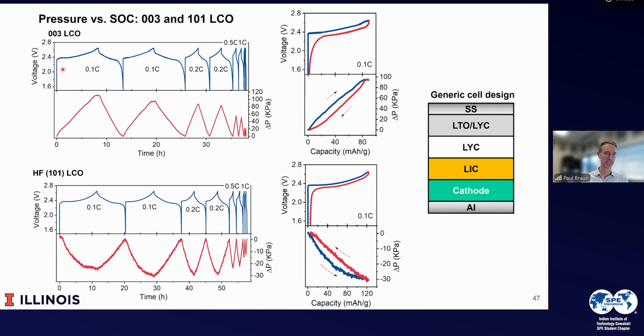And so here you can see that the pressure is about 100 kPa, and it is positive with state of charge. Here, by varying the orientation, we can see the pressure is only about 30 kPa, and it is negative with state of charge. So here we've completely switched it from a system that is expanding during charging to contracting during charging. And we want it to contract during charge because when you're charging, the anode is getting bigger. So you want the cathode to get smaller. And during discharge, the cathode's getting bigger. So you want the anode to get smaller.